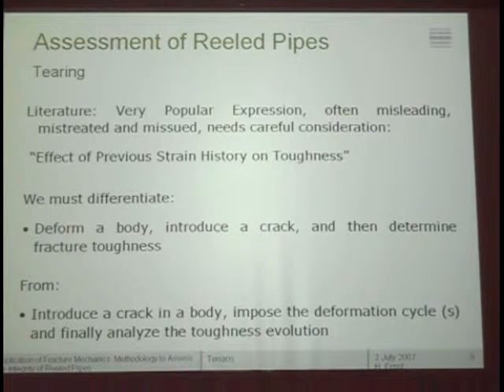Well, just to start very slowly, one sentence that you see very often in the literature, that we believe is a little misleading and mistreated and misused sometimes, and needs careful consideration, is this: the effect of previous strain history on toughness. And this is what we mean by that. We must differentiate between deforming a body, introducing a crack, and then determining the fracture toughness, which is what you usually find in the literature, from what is happening here, which is something different.